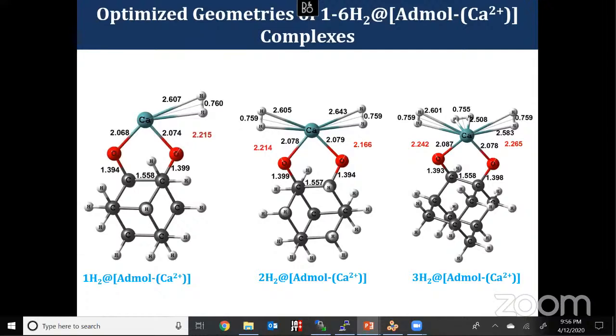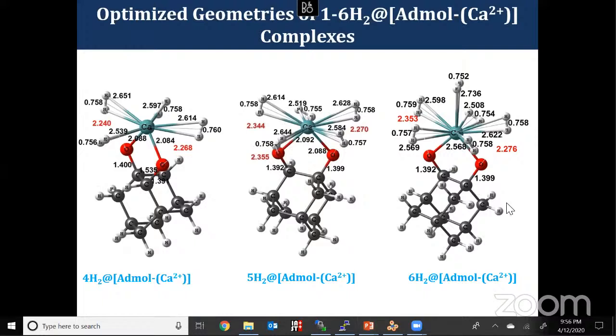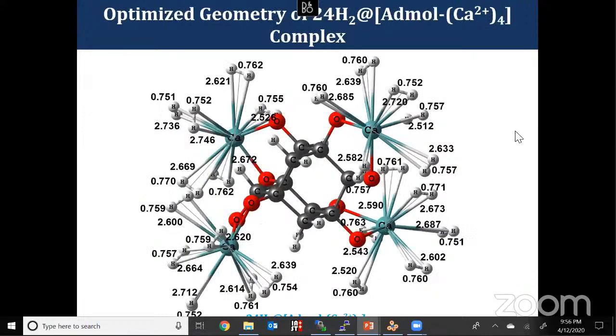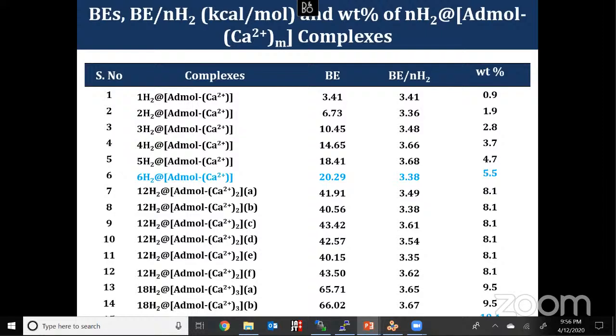And this is for the calcium system. For calcium, sorry, we can store 24 hydrogen molecules. For a single unit, we can store 6 hydrogen molecules. Still, there is no repulsion between hydrogen molecules. And we calculated the binding energy. Here also we found that the complex adsorbing the maximum number of hydrogen molecules has higher binding energy as well as weight percentage. That means we can use this moiety alone, or we can functionalize this adamantane in an appropriate metal organic framework, add open metal sites on it, and use that for a particular hydrogen storage application.